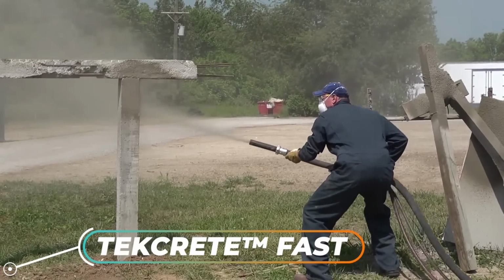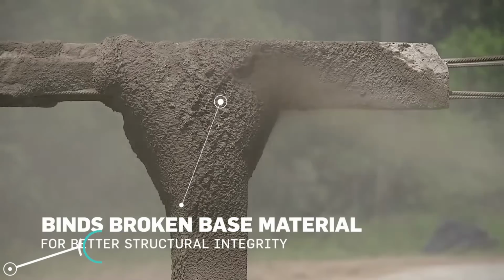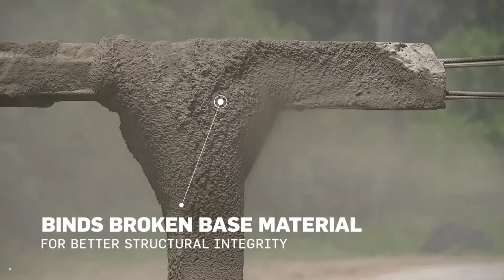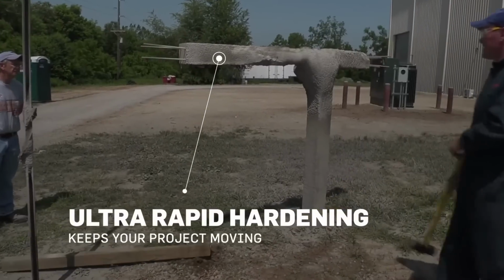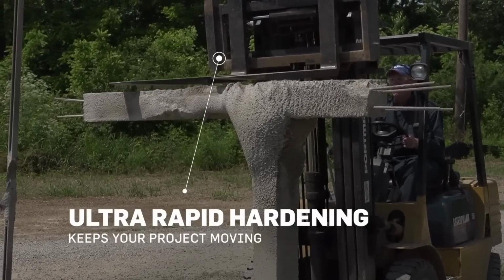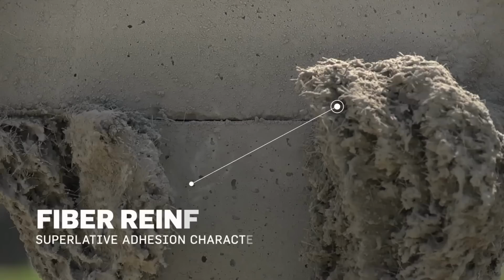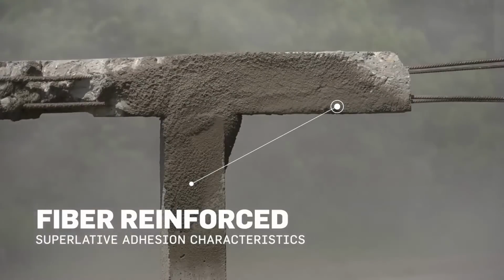Tekcrete Fast is a rapid-setting dry mix shotcrete developed by Minova for structural support in mining, tunneling, and underground construction. It reaches over 3,000 pounds per square inch compressive strength within 1 hour and 8,000 to 10,000 pounds per square inch in 28 days. With a quick setting time, it can be applied within minutes, allowing for immediate stabilization.